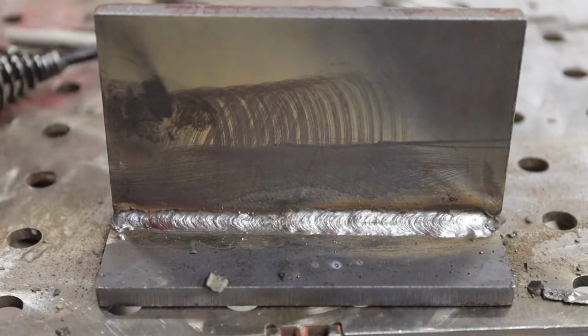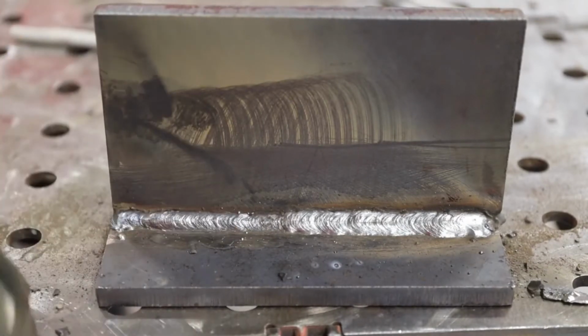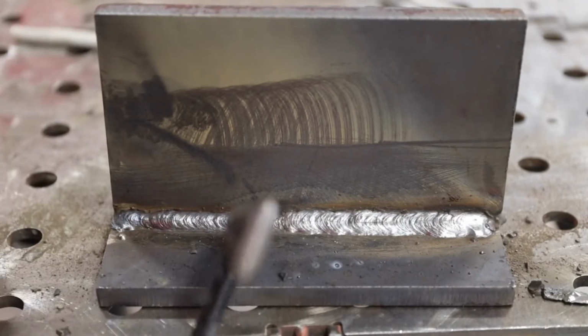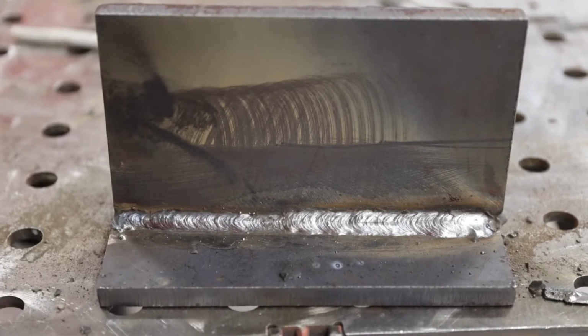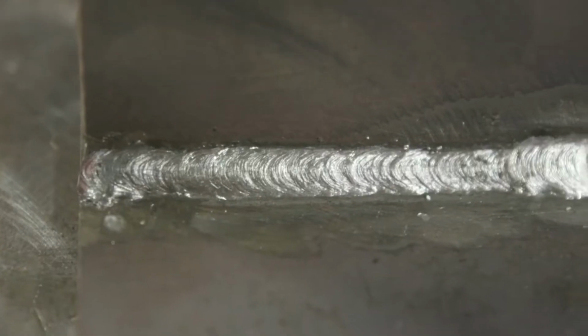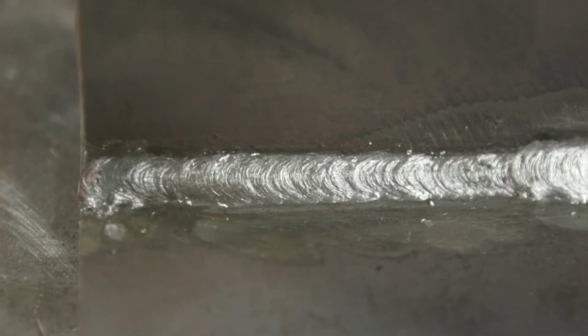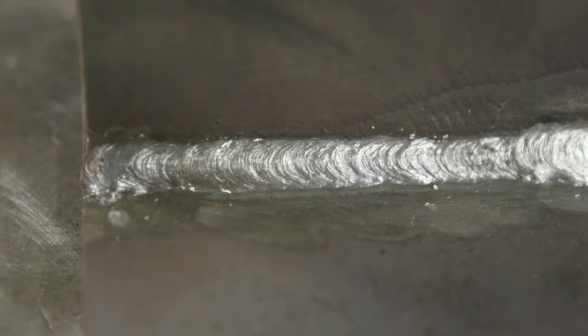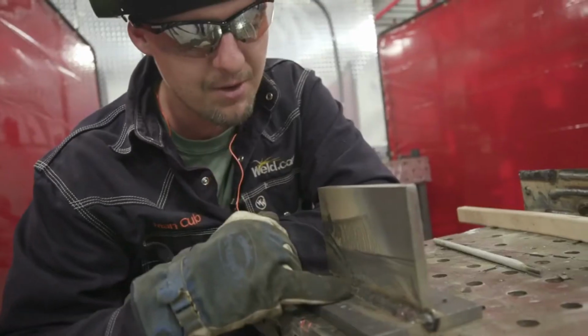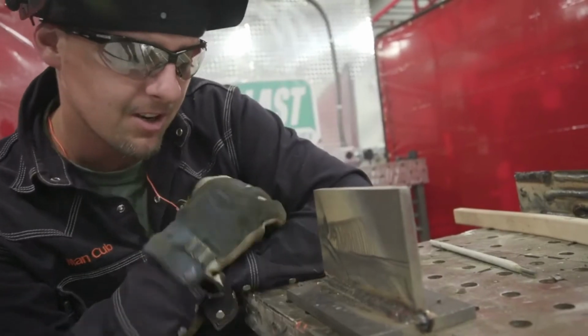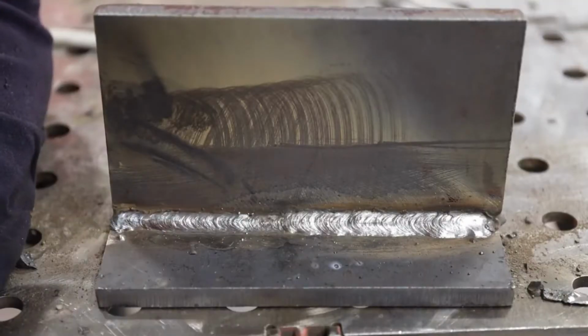Alright, just by looking at this, we can tell 1/8 inch ran with no problem. Good tie-ins on our toes on the side of the base metal. No problem, no porosity, no hump up right here. So the hot start intensity is doing its job. It's working 100%. So the 5/32 rod, just by looking at it, we have a good, nice start tie-in right here, a restart.